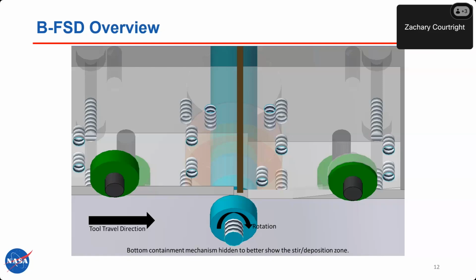But with this redundancy, we were able to get rid of that. Ultimately, there was one primary redundancy point, and that was bolting the entire containment mechanism to a rigid block that is adhered to the machine outside of the spindle. By doing that, we were able to essentially eliminate any amount of torque or movement that could happen in the containment plate, and that eliminated that issue.